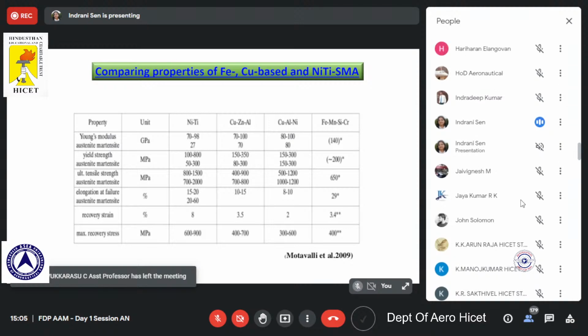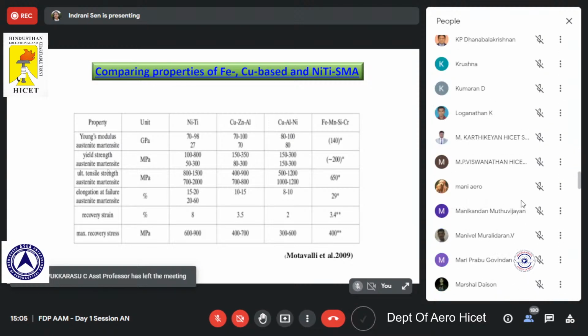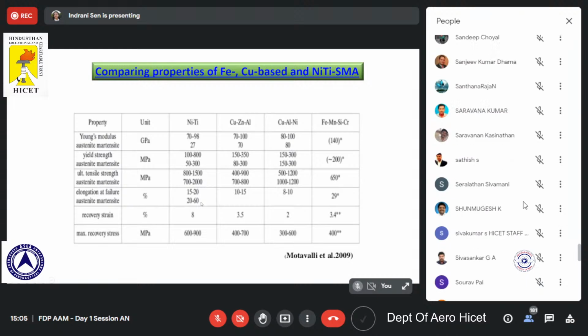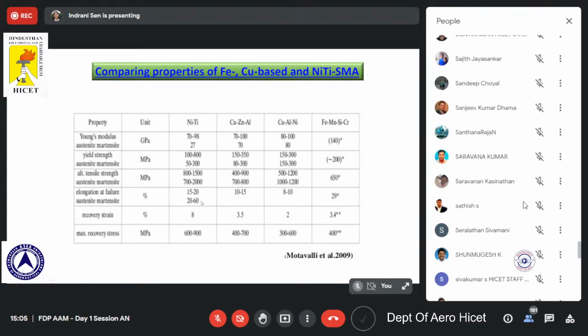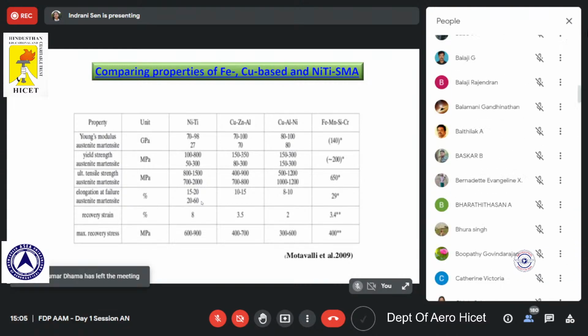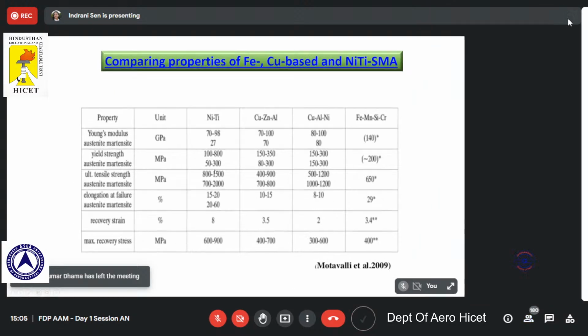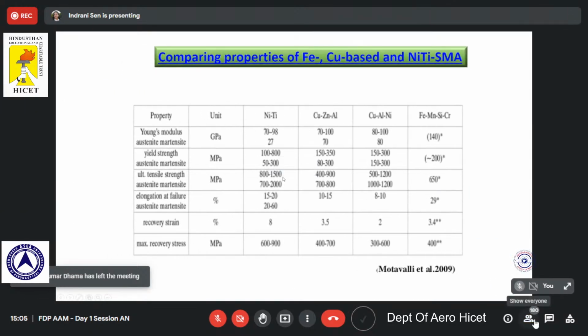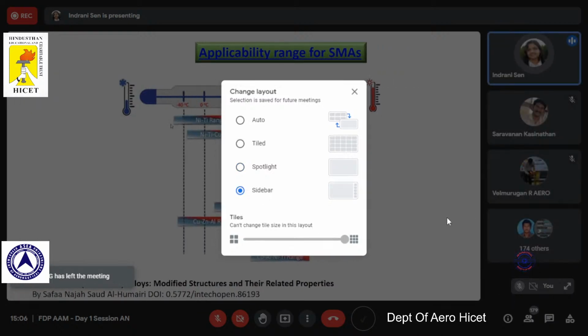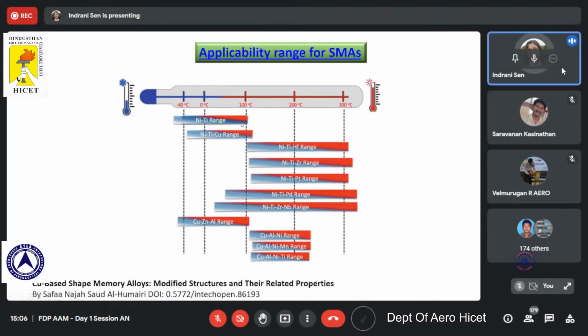Okay. Fine. So apart from that, strength and elongation are also quite high for nickel titanium, quite optimum values that we can obtain, and that is one of the reasons that nickel titanium has gained popularity over all different kinds of shape memory alloys. And not only that, if we are talking about the temperature range over which it can be used, you can see that nickel titanium is typically used from very low temperature, around minus 50 to plus 100 degrees centigrade, quite a good span of temperature which is used for regular usage.